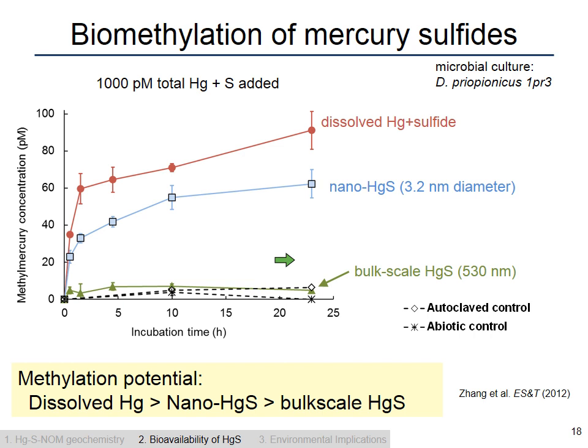And then the other thing that is unique about this result is that we have much greater methylmercury produced with the nanoparticles compared to the microscale particles. And that's a result that would not have been predicted by a chemical equilibrium approach, which would have said that the activity of these, regardless if it's nanocrystalline or not, would have been the same. And equilibrium would not have predicted this result. So this is an experiment where we have the same amount of mercury added, but different forms.